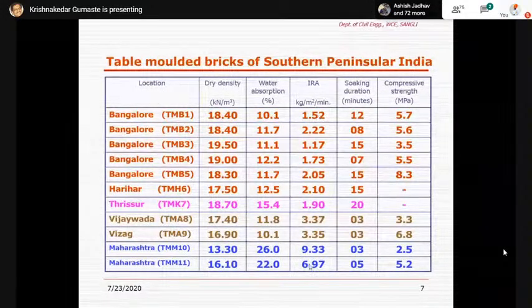Why is this duration important? You can see that the majority of the bricks show an IRA between 1.5 to 3 or 3.5, whereas bricks which had very high water absorption also show a very high IRA, in terms of 7 to 9 kg per meter square per minute, which means that the higher the value, the brick has a higher capacity of absorbing water within a small duration of time.